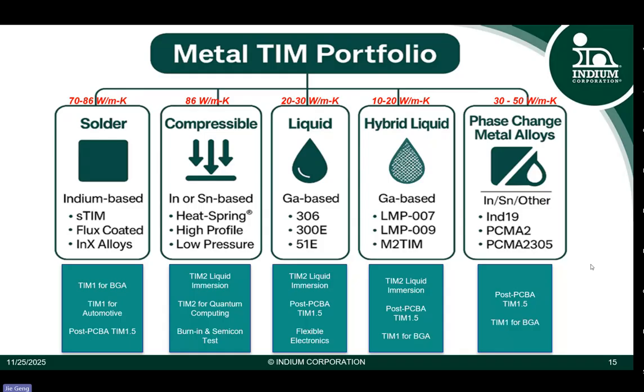The third category is the liquid metals, gallium-based liquid metals. Because it's liquid, it's easy to fill the air gaps at the interface. The next category is hybrid liquid, where we include liquid metal paste or other liquid metal, either as filler or matrix. We call that a hybrid liquid. The last category is phase change metal materials. This kind of metal material has relatively low melting points. The melting range is between 60 degrees Celsius and 100 degrees Celsius, and depending on the composition, we can adjust that.